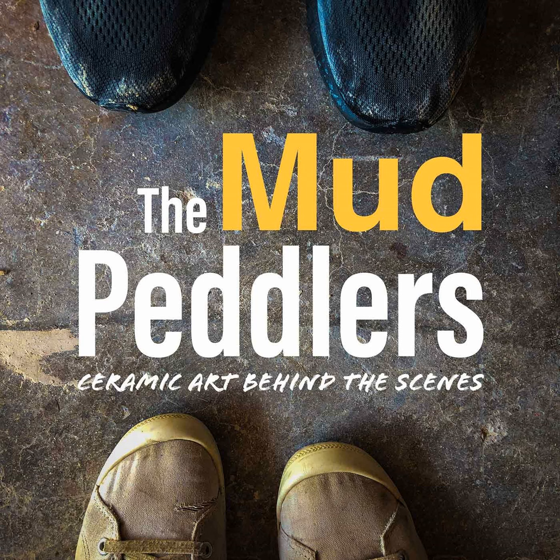Now for Dante's news. A lot of you know I've been trying to figure out ancient copper glaze. I've essentially figured out what it is. The first two months I thought maybe it was a tin-chrome glaze — I hate tin-chrome, they're purple with extra steps. Then I thought it was a crystal glaze, but crystal glazes have a high amount of zinc, and a friend pointed out that high levels of zinc and iron don't really like each other — that's why you don't see a lot of red crystal glazes on the market.